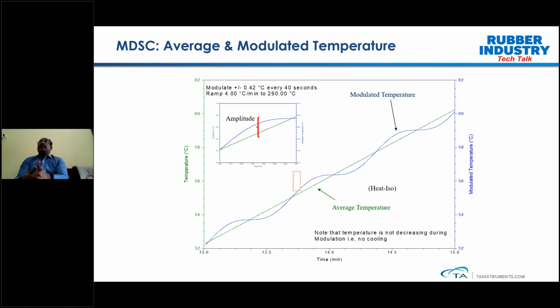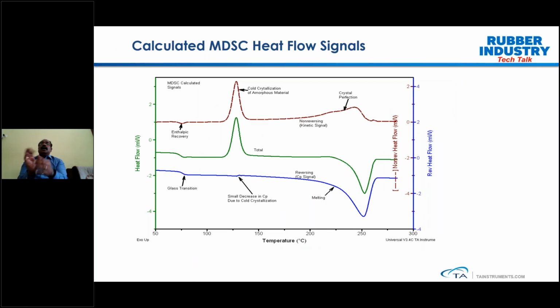This way, the modulated DSC will give three signals. One is total heat flow, which is similar to the normal heat flow you get for the standard heating rate. But apart from that, you get two more heat flow signals: the reversible heat flow, which is the blue curve, and then the non-reversible heat flow, which is the brown curve. If you closely look at the thermogram of each individual heat flow signal, you can see the total heat flow, the green one, carries all the information. For example, in this case, we can see clearly the step change followed by cold crystallization and then melting. When you look at the reversible heat flow, it is basically only showing the transitions which are reversible or thermodynamic in nature.